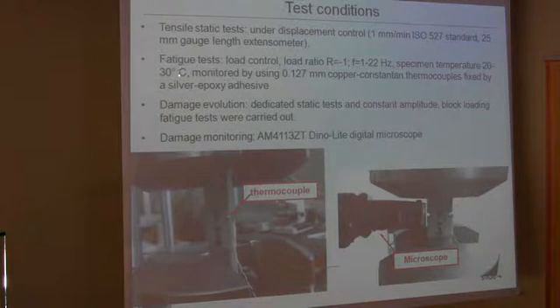Test conditions: we performed tensile static tests under displacement control according to international standard, and fatigue tests under load control, imposing a load ratio equal to -1, that means push-pull fatigue. The test frequency ranged between 1 and 22 Hz depending on the applied stress amplitude, in order to keep the material temperature below 30 degrees. The temperature was monitored by gluing a thermocouple at the notch tip, and the damage evolution was investigated by carrying out dedicated tensile static and constant amplitude fatigue tests, and the damage was monitored on board by using a digital microscope.